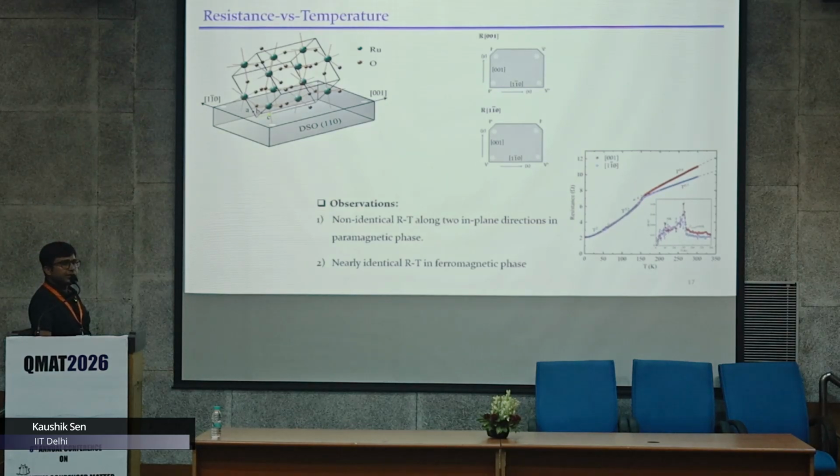Now T square dependence is a Fermi liquid, as you said, it's right, but there is also another term that can give you T square, that is electron and coherent magnon scattering. And magnon you can expect here, right? It's a ferromagnet system, and I believe at very low temperature magnons are coherent. That also gives rise to T square dependence. But if the magnons are not coherent near the transition, then you can get this T to the power 3/2 dependence. So that's our understanding so far.